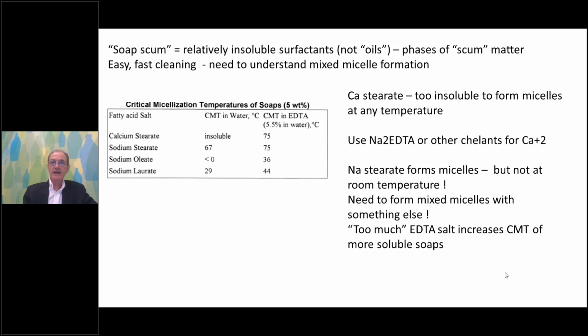Now, as surfactant scientists, we know that soap scum, calcium stearate, really is an insoluble surfactant that we're dealing with. So its phases matter for our cleaning it. Calcium stearate is too insoluble to form micelles at any temperature, right? So typically in our formulations, we will add a chelant like EDTA salt in order to generate sodium stearate. Now, sodium stearate forms micelles, but not at room temperature. We can see the critical micellization temperature is 67 C, pretty warm.